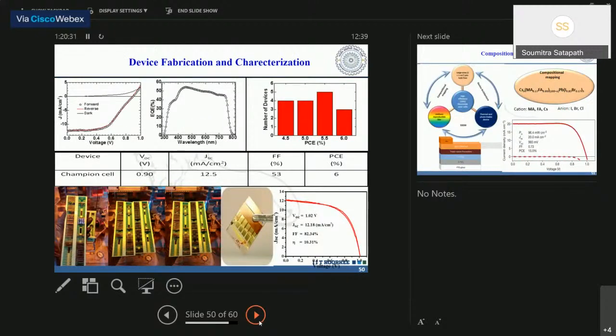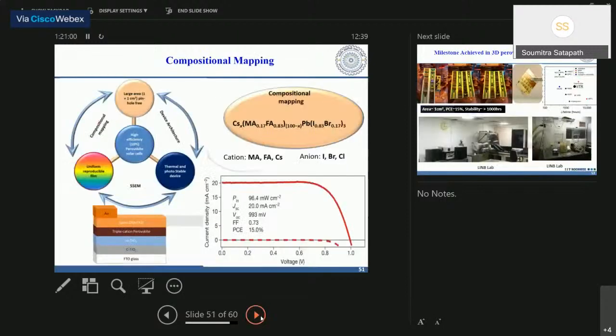Out of curiosity, we wanted to make a solar cell, and to our surprise this room temperature approach gave us a reproducible solar cell where the champion solar cell has an efficiency of 6%. That's good. A solar cell without a glove box, by the dual solvent method, with an efficiency of 6%. These are the pictures of solar cells which we made in the lab; we make almost 80 to 100 solar cells per day. But 6% will not do the job. We have to improve it.